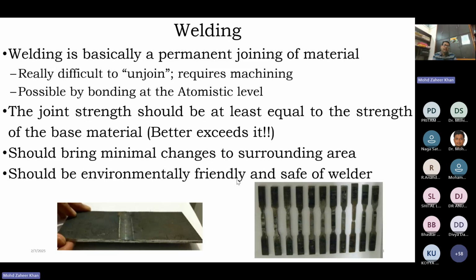As you can see in this figure, there are two plates that have been welded by the friction stir welding process. And just a minute, I will take out the laser pointer. Yeah. So you can see these are two pieces of metal. They have been joined in the center. And after joining, strips have been machined out perpendicular to the direction in which welding has been carried out. After taking out the strips, flat tensile test specimens have been created, as you can see in these photographs. These transverse tensile test specimens have been put in a UTM, a tensile testing machine, and the tensile load has been applied, and these joined pieces of plates have been fractured.